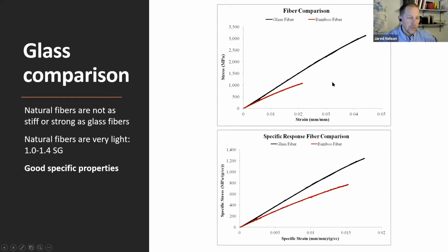Straight off the bat, this is a stress strain curve that compares our glass fiber to our bamboo fiber. Two key things to take away from this. We can look at the endpoint here of the bamboo, and we can see that we're failing at about 1,000 MPa. That's all well and good. What's an MPa? Doesn't really matter for us at this particular time. Comparatively, we can look at a glass fiber, and that's failing at roughly 3,000 MPa. So there's a factor of 3 difference in this strength. We can also see that our strain at failure is just over 2 and just over 4. So basically, the fiberglass is stronger, and it stretches more before it breaks. If we look at that off the cuff, we think, why even consider bamboo?